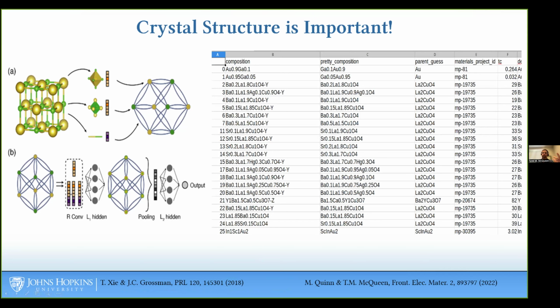The other part, which is where 90% of the work actually was, we needed structural information to associate with TC values. And Supercon didn't have that, right? So through a combination of manual, automated, and semi-automated methods, my student Maggie assigned, for every entry in Supercon, and a whole bunch more entries that we added to it as well, and I'll get to that in a minute, information about the structure. Now, for almost all of these, there isn't the detailed, like, here's the exact lattice parameter, here's the exact atomic positions in the crystal structure, but at least the structure type. And if you'll notice, that's useful if you're going to represent things as a graph, that it doesn't capture these details of like distances, but it captures very well the connectivity, right? So we added to the Supercon database everything that was required for understanding the connectivity.